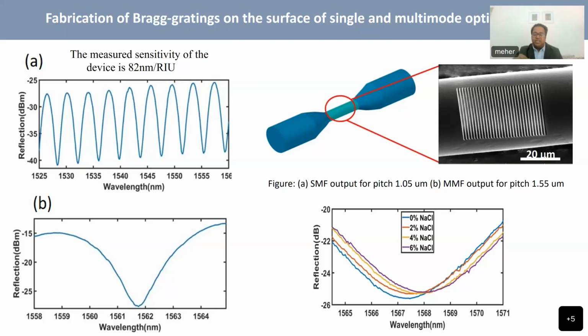And when we have a refractive index change, we see this shift in peaks, and it was experimentally verified. Then we did simulations also, and the simulation results and the experimental results were very much in alignment. We found that the measured sensitivity is around 82 nanometers per refractive index unit. RIU is the unit of refractive index. So this sensitivity is good, but the process of making these sensors was very complex.